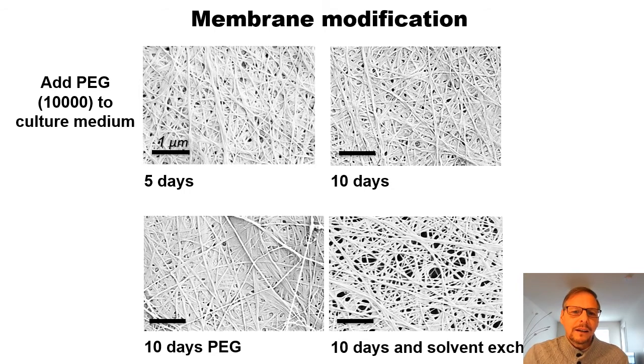And you can see here how the structure, the morphology of the membrane, is changed. In the bottom right, by the way, I show how the porosity can also be affected by solvent exchange. So we now have a much more open membrane. So quite nicely, we can control the porosity and permeability of membranes.